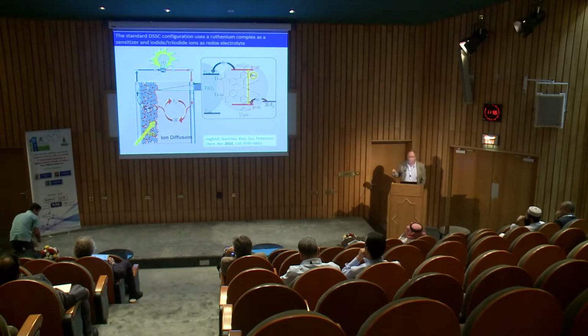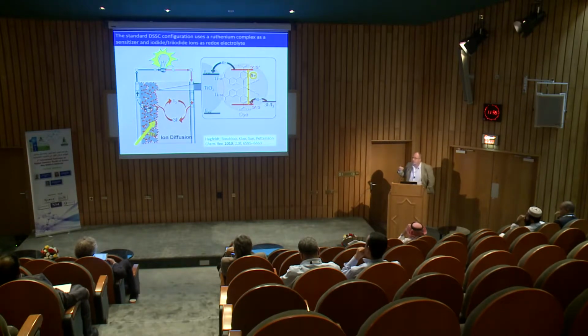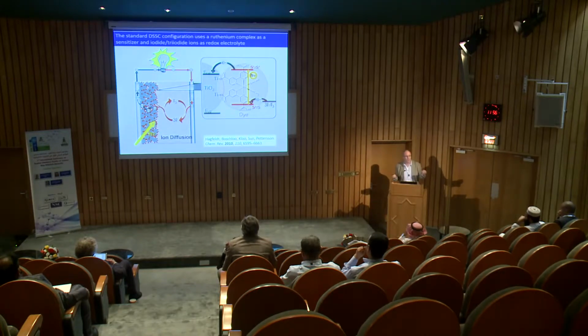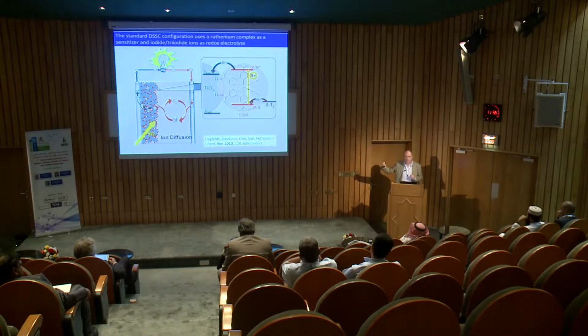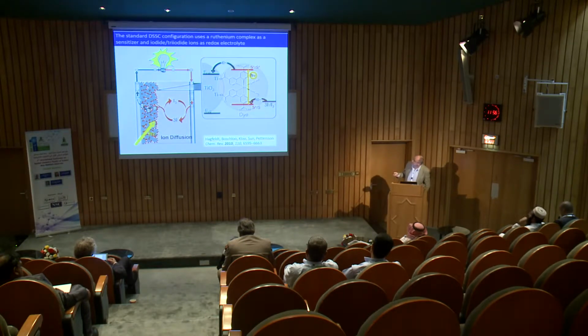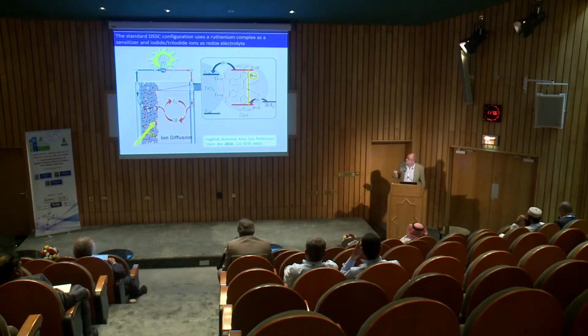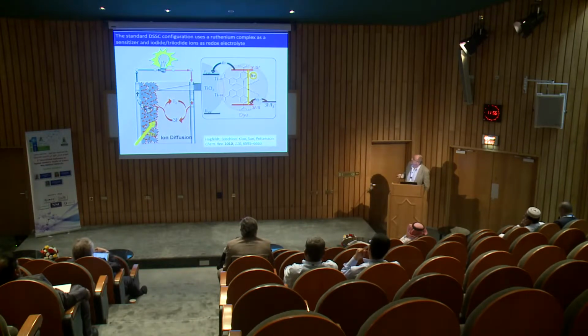We could also understand that the dye molecule itself could separate the charges, because the orbital architecture of the dye is such that when we excite the electron to the excited state, we populate the pi star orbital of the carboxylic group, and that's exactly where we want the electron to be because that is where we have the TiO2 surface. And the remaining hole here is very much located on the sulfur atom on the ligands. So when we do the excitation, the electron moves to the TiO2 surface, the hole moves out to the electrolyte, and in that way the dye can separate the charge, and then the electron can be transported through a diffusion mechanism. And also Professor Bisquert had described in more detail how the transport works with the trapping, detrapping mechanism. So that's the overall picture.